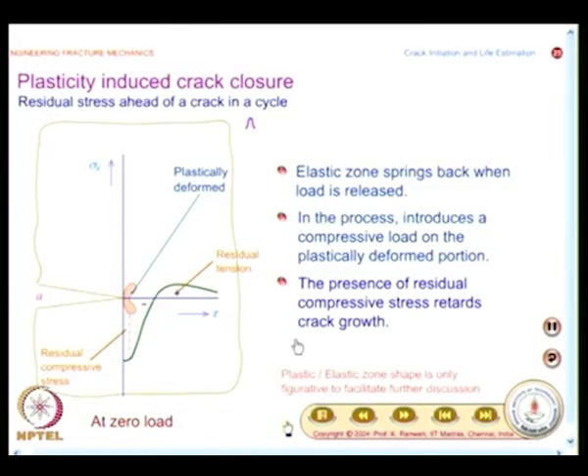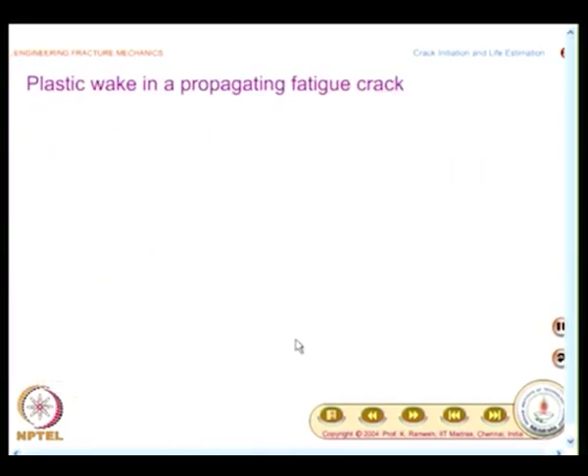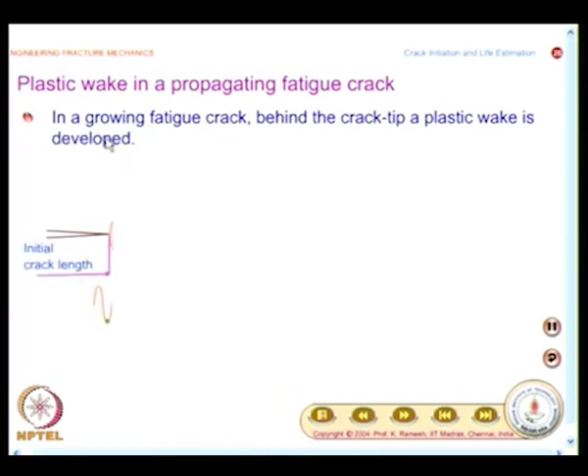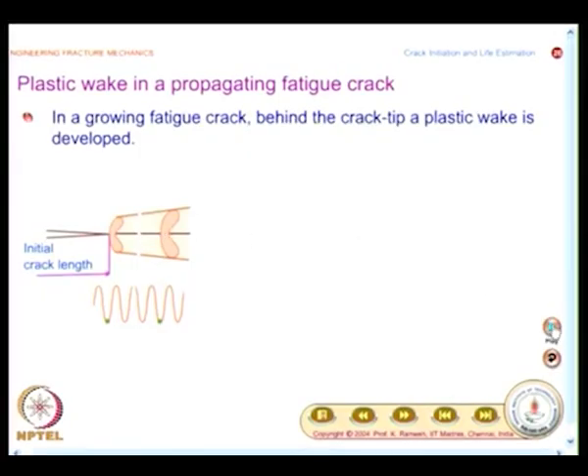Now you have to see, if I have multiple cycles, the crack will go through a plastic wake. We will see that also. I have a very nice set of animations and we will see through that. In a growing fatigue crack, behind the crack tip a plastic wake is developed. I have initial crack length, and what is shown here indicates that you are having a cyclical loading. You are seeing at the end of one cycle what happens. After several cycles, what happens? The crack is growing in length. So when the crack grows in length, the plastic zone also will grow in shape. It is not going to remain the same size, it is going to increase.